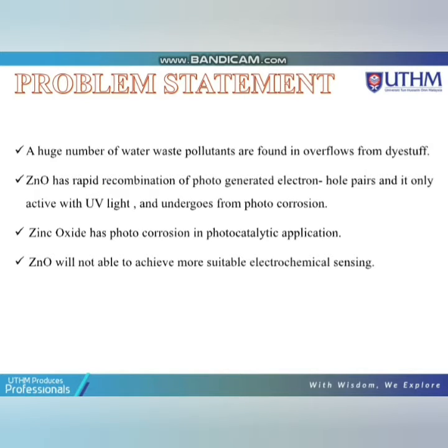Problem statement. A huge amount of wastewater pollution comes from dyestuff overflow. Zinc oxide has rapid recombination of photogenerated electron-hole pairs, it is only active under UV light, and it suffers from photocorrosion. Zinc oxide also is not able to achieve suitable electrochemical sensing. To overcome this limitation, zinc oxide has to be combined with other materials such as metal, semiconductor, and nanocarbon.